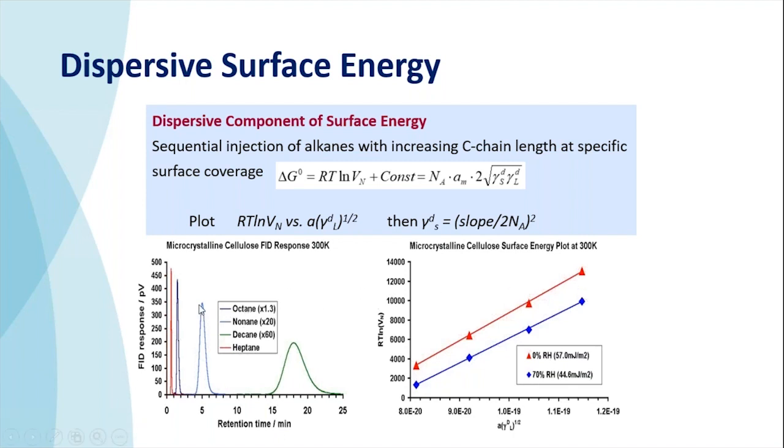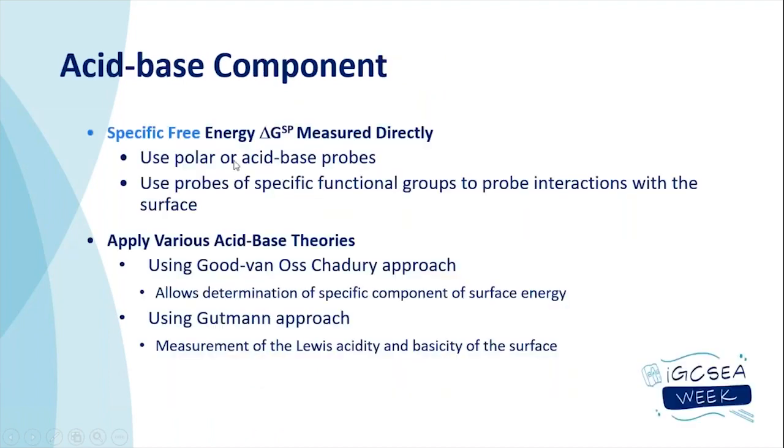Before I get to that point, just as a reminder for those not familiar, on measuring surface energy by inverse gas chromatography, we typically use a series of straight chain alkanes: nonane, octane, heptane, decane. There are a couple of different approaches in the literature, but essentially you inject a few nonpolar or dispersive molecules, and you get the dispersive component of the surface energy, this gamma D. And then you use some Lewis acid-base molecules.